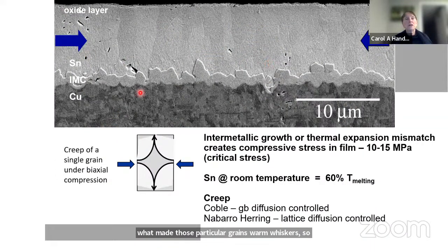This is the tin film, in this case on a copper substrate. And at room temperature, the tin and the copper react to form an intermetallic. So remember that tin at room temperature is about 60% of the melting point. So there's plenty of diffusion that happens, and so these intermetallics grow. So what happens in this particular situation is when the intermetallics grow, they create a compressive stress in the film. So you don't even have to have a mismatch in the thermal expansion coefficient.